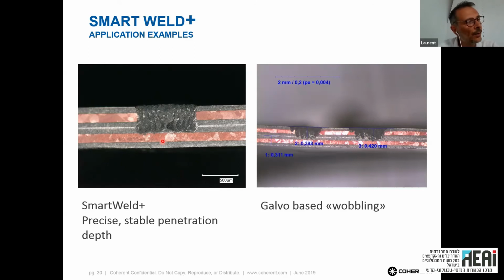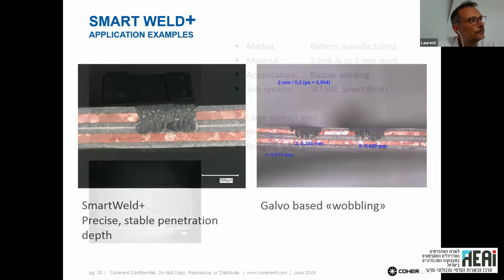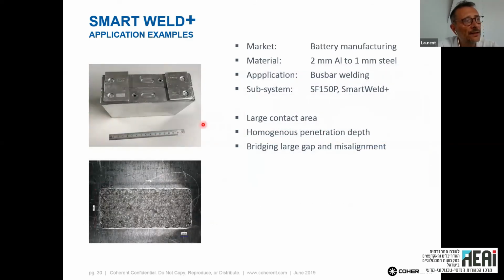So with SmartWeld Plus, because every spot is exactly the same side by side, you are really able to stabilize the penetration depth. Again, some battery. In this case, we speak about 2 millimeter aluminum to 1 millimeter steel. It's again a busbar.